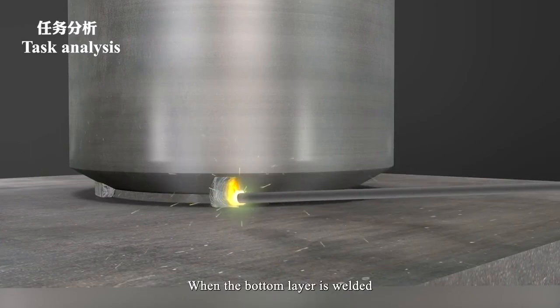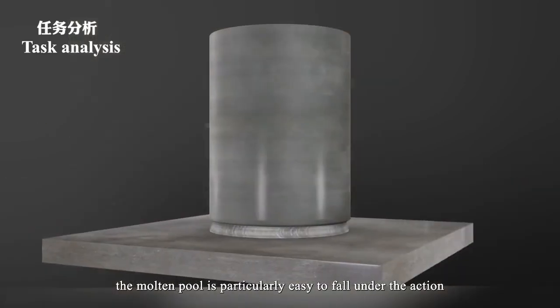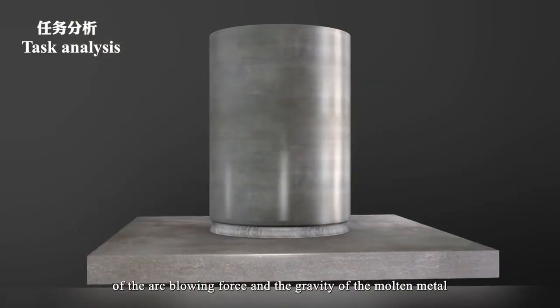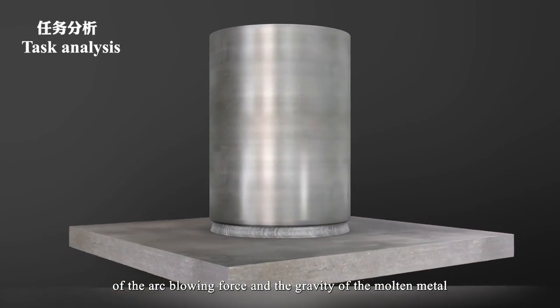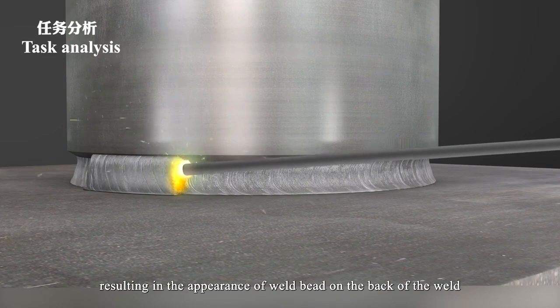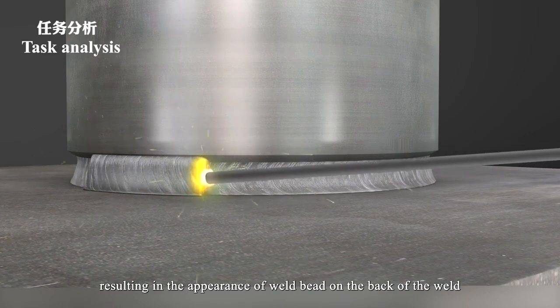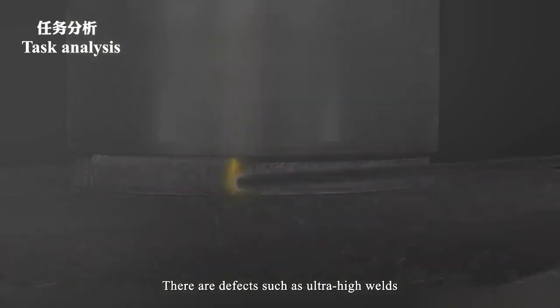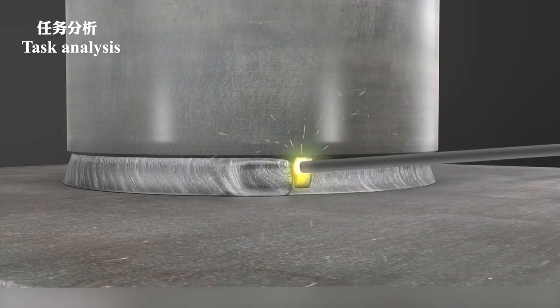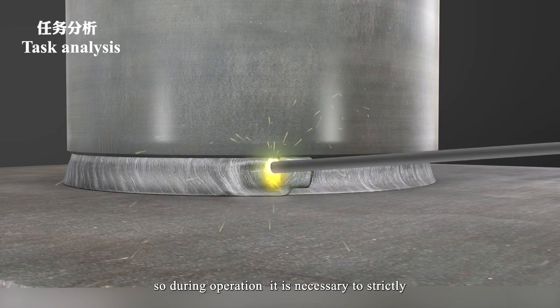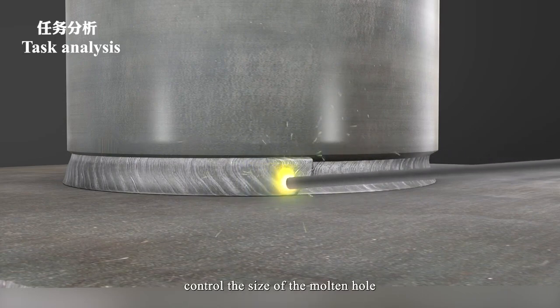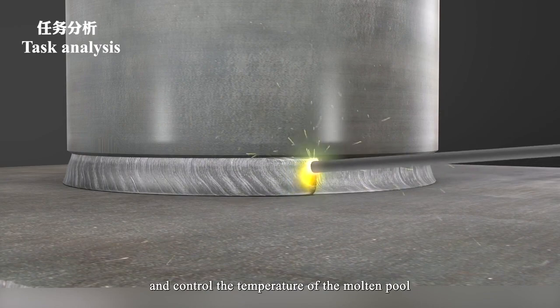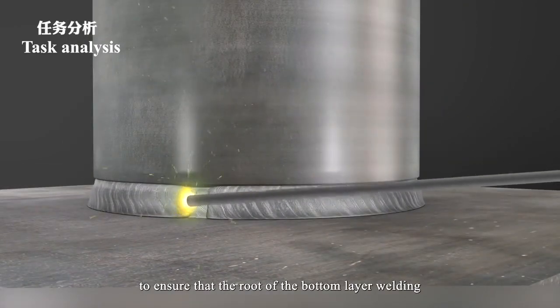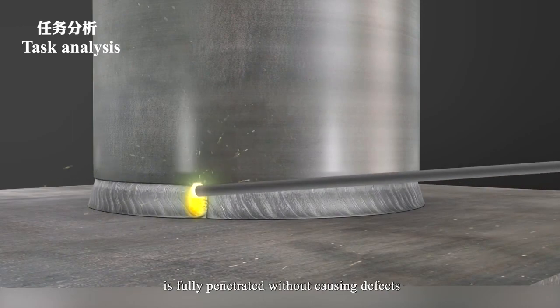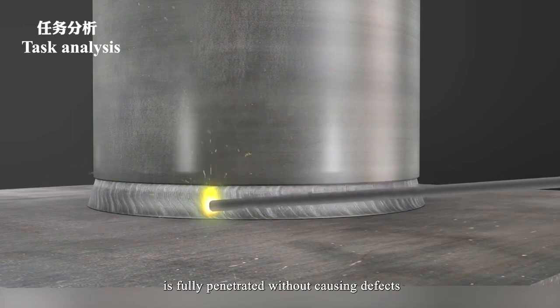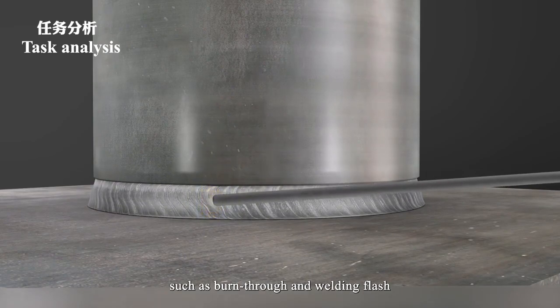When the bottom layer is welded, the molten pool is particularly easy to fall under the action of the arc blowing force and the gravity of the molten metal, resulting in defects such as weld bead on the back of the weld and excessive weld height. So during operation, it is necessary to strictly control the size of the molten hole and control the temperature of the molten pool to ensure that the root of bottom layer welding is fully penetrated without causing defects such as burn-through and welding flash.